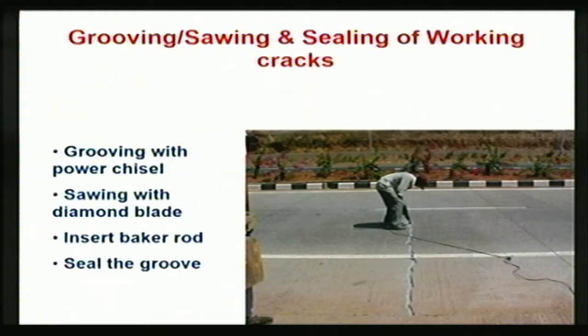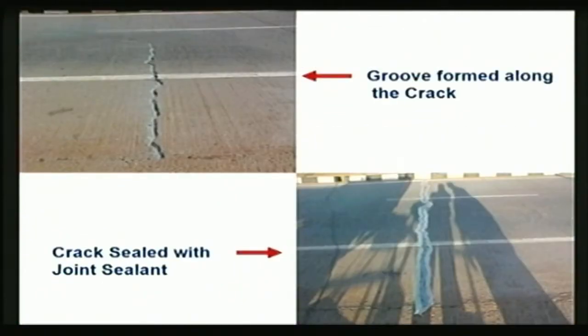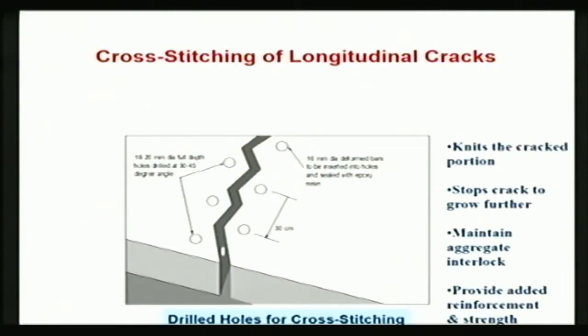So those joints actually are working as a joint. They are accommodating the expansion and contraction of the slab. So those cracks may be treated like a joint. And what do we do at the joint? We create a groove at the joint and seal it so that water and sand and silt do not enter into the joint. Same thing we can do here. If it is a working crack, then just prepare a groove along the contour of the crack and then fill it with any polysulfide or silicone sealant, whatever we use for the joints normally.